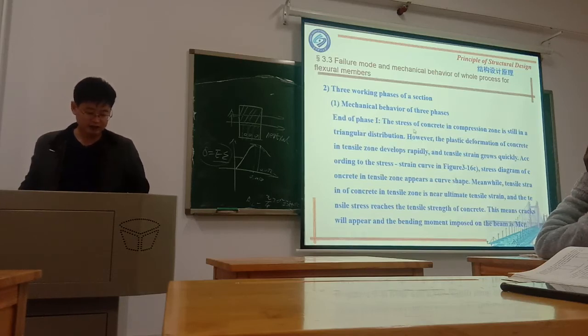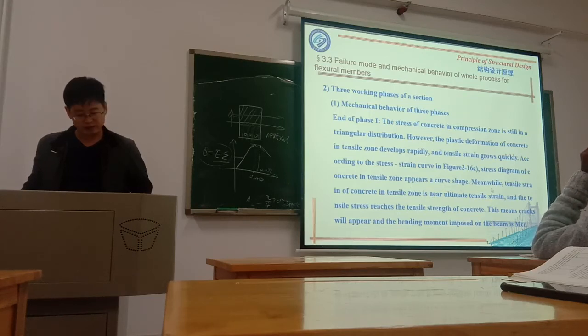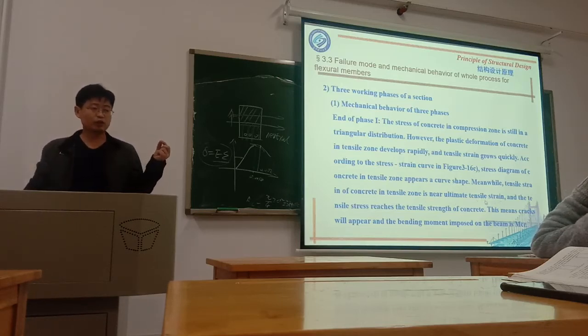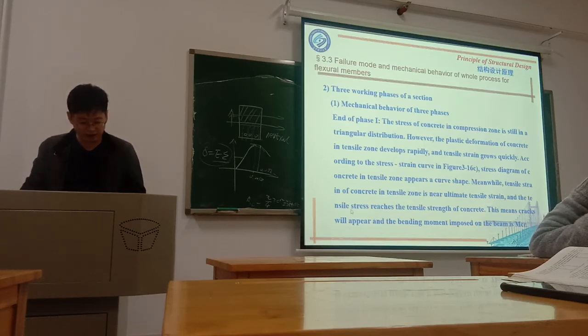At the end of phase 1, the stress of the concrete in compression is still in triangle distribution. However, the plastic deformation of the concrete in tension develops rapidly. As the tensile strain grows quickly, according to the stress-strain curve, the stress diagram of the concrete in tension appears as a curve shape. Meanwhile, the tensile strain of the concrete in tension is near the ultimate tensile strain. That means the crack is going to appear. Once it reaches the tensile strain of the concrete, it just cracks. So actually, the tensile stress reaches the tensile strength of the concrete. That means the concrete will crack.